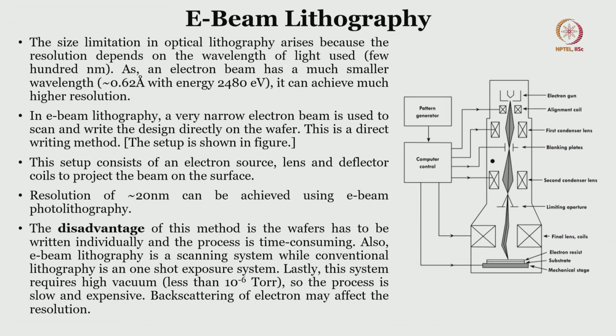In E-beam lithography, a very narrow beam, as I told you, is used to scan and write directly onto the wafer. This is a direct writing method and the schematic is shown here in the figure. A resolution of 20 nanometers can be achieved, while in photolithography, UV lithography, we are somewhere in the micrometer range. The limitation of this method is that wafers have to be written individually and the process is time consuming.